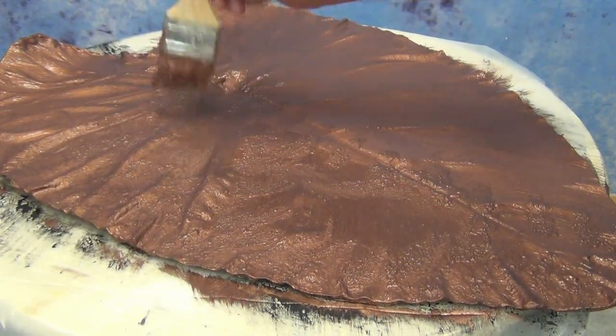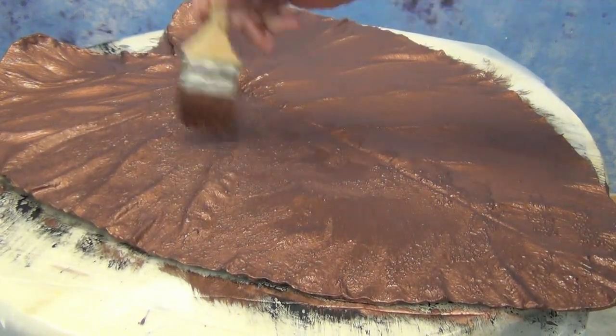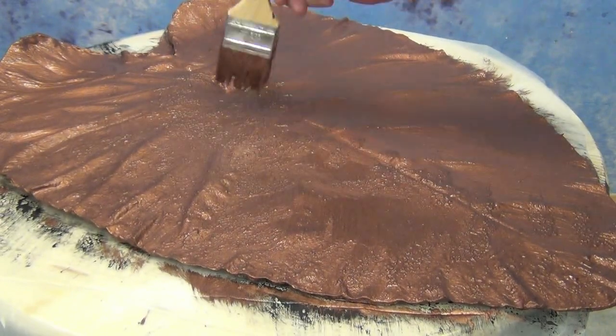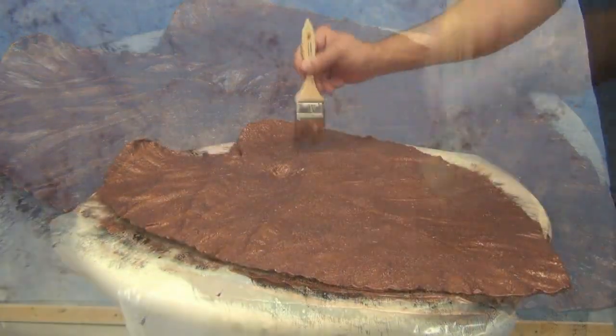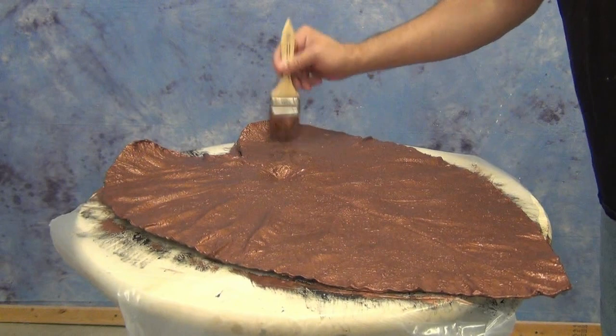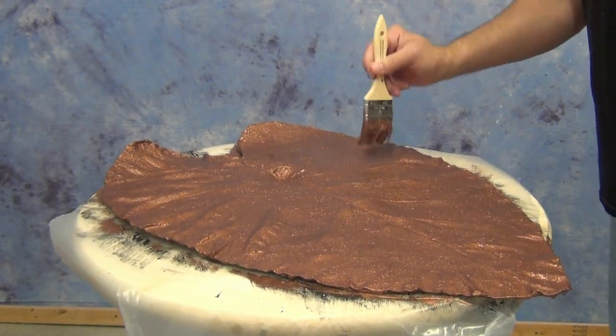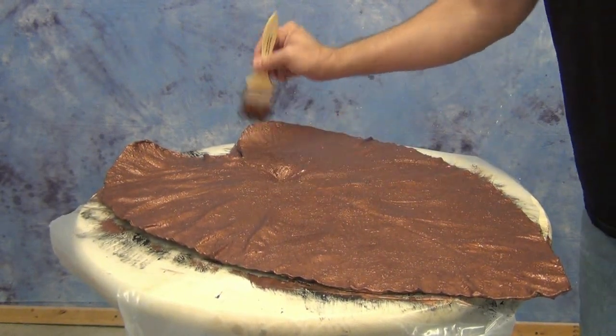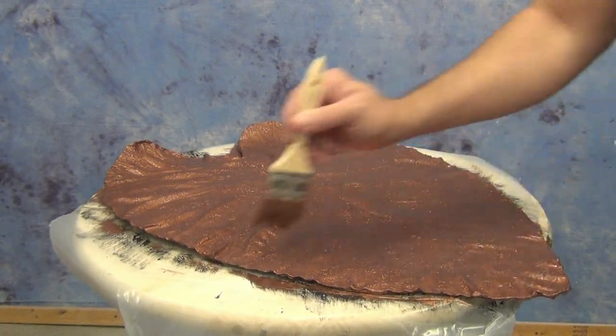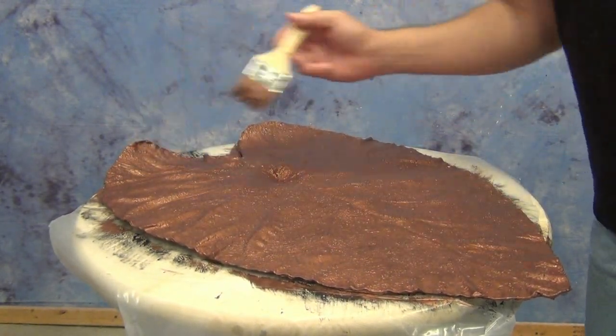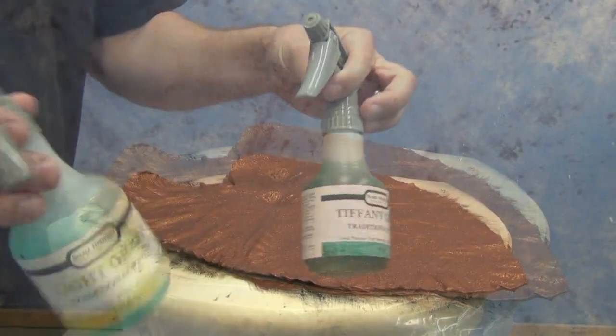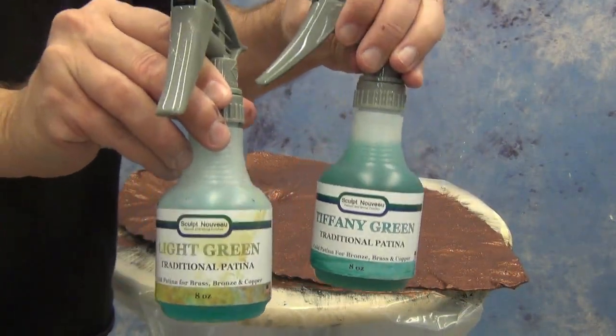And once we've done that, we need to very quickly transition to applying our patina. And that's an acid patina, so we want to make sure we immediately apply that while that Copper B metal coating is wet on the second coat. If we allow that to dry, we're going to get little if no reaction on the surface of our part. So now that we have our second layer applied, we're ready for our patina.